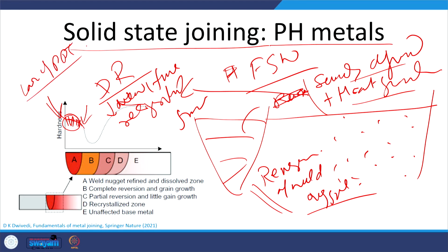Okay. But apart from this loss, there will be little work hardening effect and little grain refinement effect, because the weld nugget is severely deformed coupled with the heat generated. So, we get dynamic recrystallization, which leads to the fine grain structure. At the same time some work hardening effect can also be observed, but if we see the zones which are a little away from the nugget zone, those which are not falling in the nugget zone,